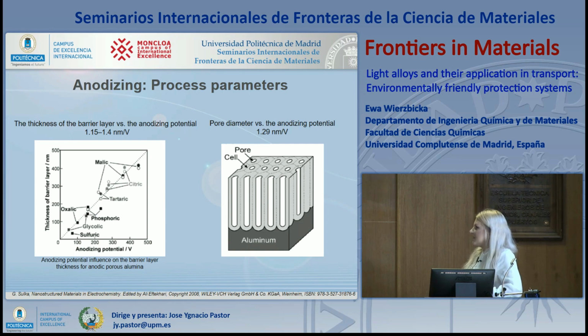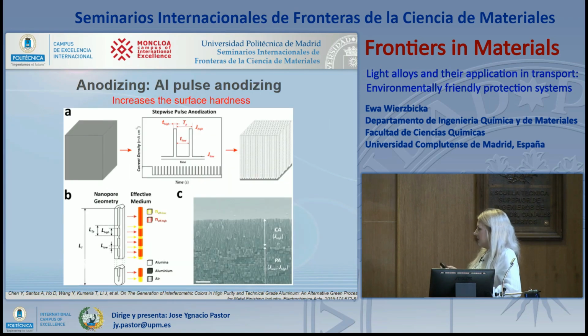The parameters of the process in the case of classic, conventional anodizing relate the thickness of the barrier layer with the potential. By applying higher voltages, we can obtain a thicker barrier layer, which is positive for anti-corrosion properties. However, at the same time, we will increase the dimension of the pores, which is a bad effect for anti-corrosion properties. So it is good to choose optimal parameters that will be good for both things.